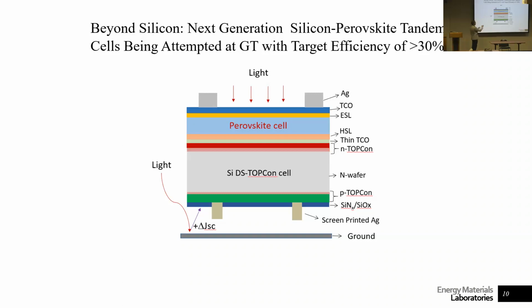So silicon solar cells make 26% devices. We put a perovskite solar cell that we can tune the band gap of so that we let some light through and are able to have an additional voltage, right? So if this cell here has 1 volt and this cell has 1.1 volt, after a lot of recombination happens, maybe we have a 1.8 volt device. That almost doubles the amount of voltage that you can have in the device, while minimizing how much loss we have in terms of the photons coming from the top.